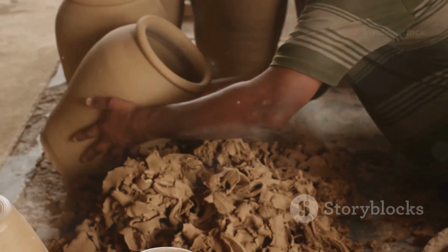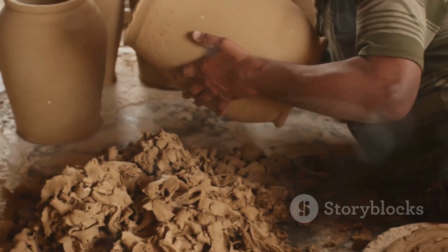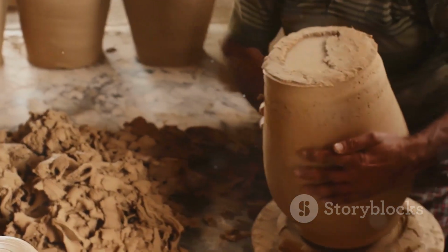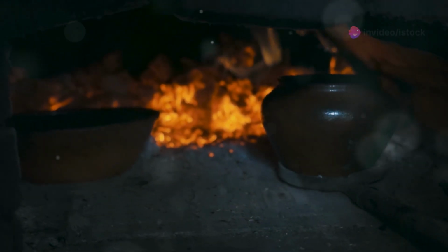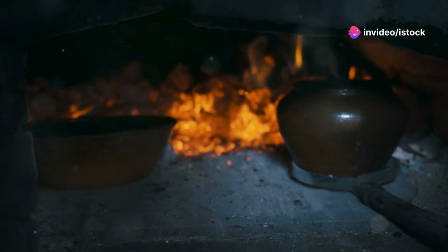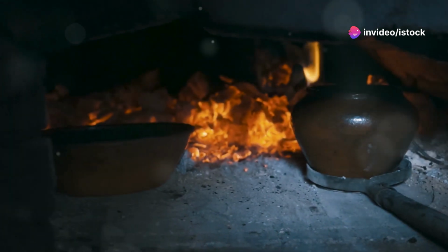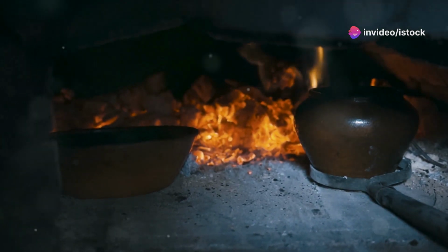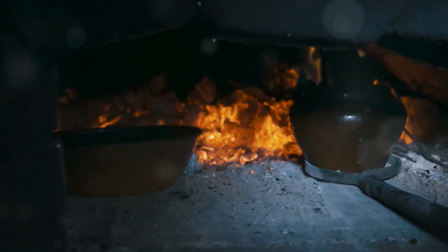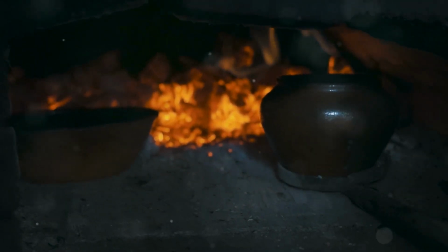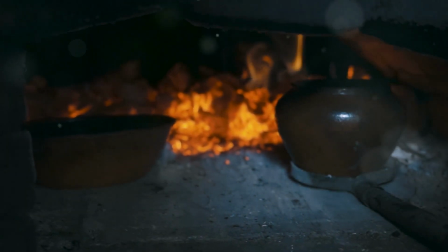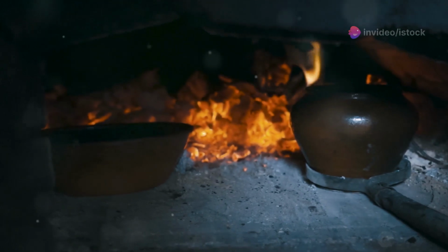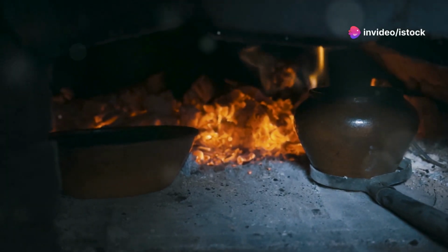The artist must monitor the kiln closely to ensure that the temperature rises at a controlled rate. The kiln is slowly heated to a high temperature. This gradual increase in temperature is crucial to avoid thermal shock, which can cause the clay to crack or explode. For bisque firing, the temperature is around 1800 degrees Fahrenheit. This high temperature hardens the clay, making it more durable and less fragile.